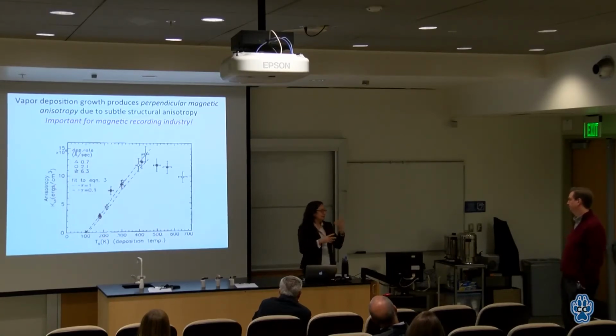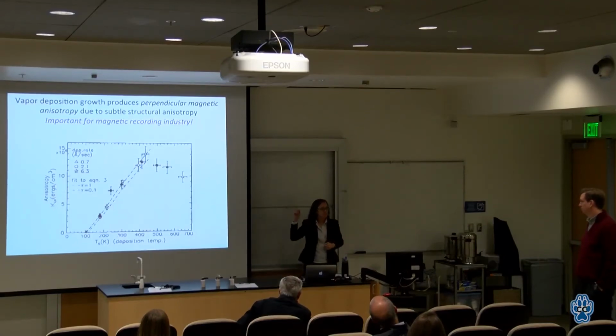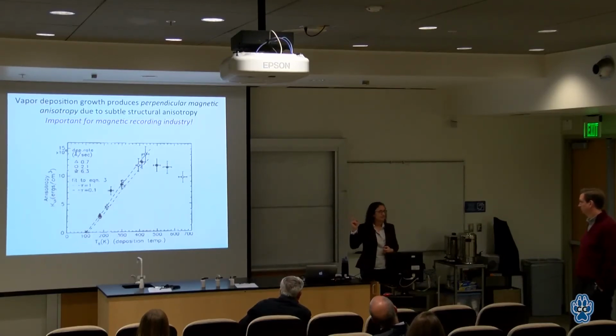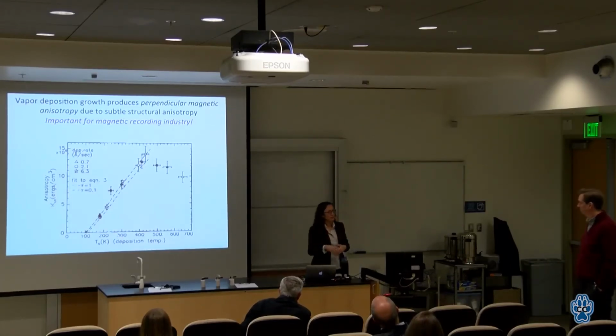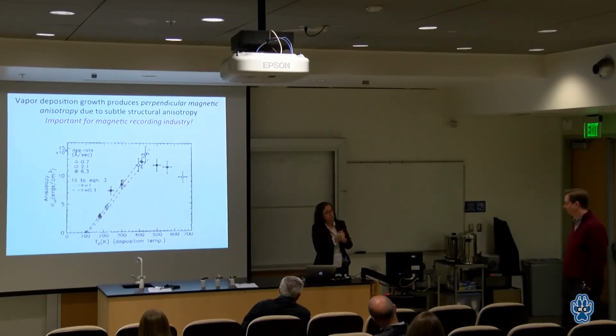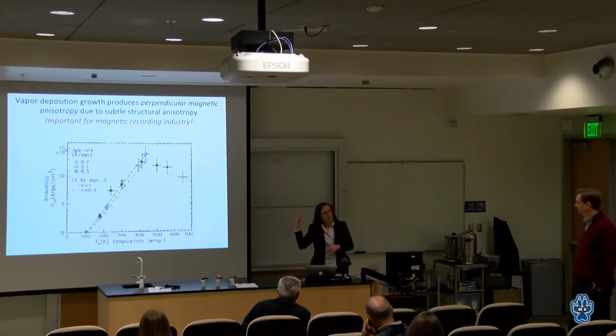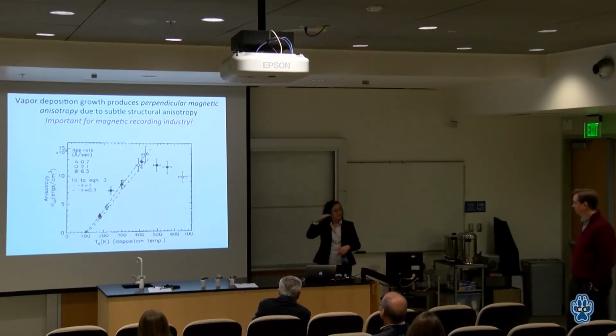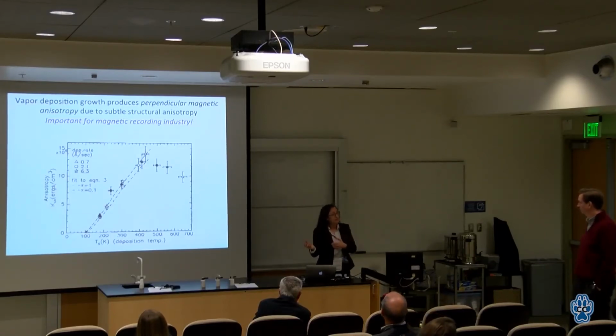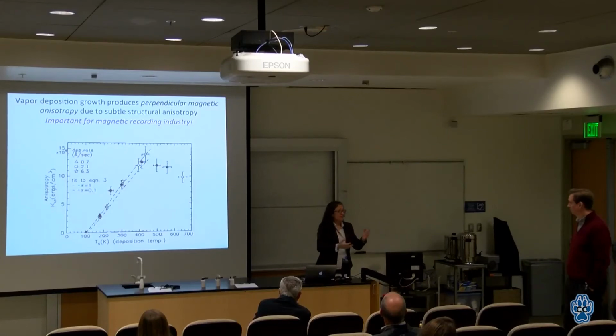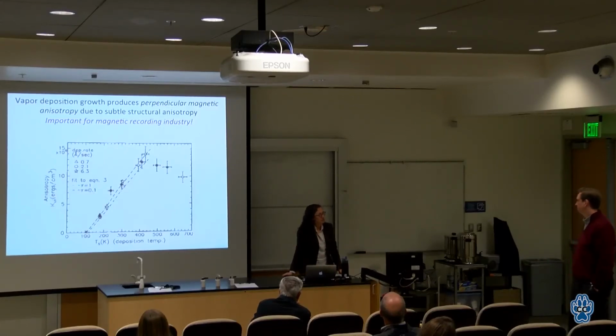And so now, the part I'm hedging on just a little bit is amorphous terbium iron. I don't think it has ever been envisioned as the material for perpendicular recording. They tend to use things like cobalt, and cobalt chromium, which has a crystalline structure, but it has to have little tiny grains. So there's a lot of details in the magnetic recording industry. So it's an exaggeration. They did use terbium iron for the magneto-optic, but not for the conventional perpendicular recording. At this point they are back to using these terbium iron-like things with these platinum overlayers and making skyrmions out of them, but that's not really a technology yet. That's a technology that everybody is hypothesizing could be in the future.